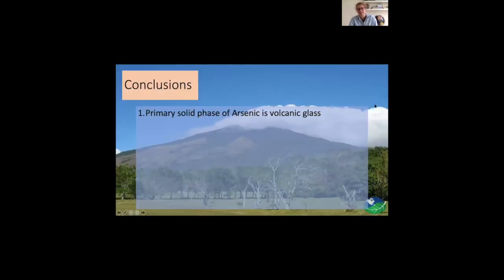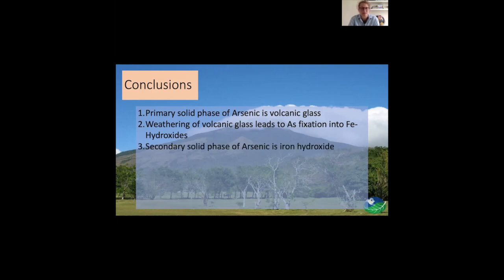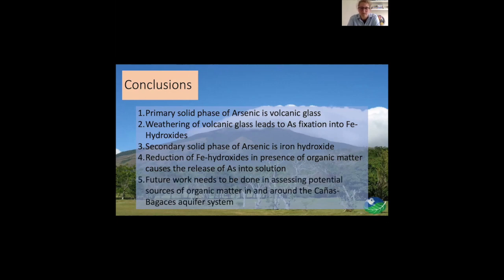So the conclusions of my thesis are that the primary solid phase of arsenic is volcanic glass. Weathering of volcanic glass leads to arsenic fixating onto the iron hydroxides. Then the secondary solid phase of arsenic is iron hydroxide, so it's sticking to these goethite minerals. Then the reduction of iron hydroxides in the presence of organic matter causes the release of arsenic into the water solution. And lastly, there needs to be future work done in assessing the potential source of organic matter. What is contributing? Is it landfill? Is it sewage? Is it just local trash pickup that is getting into the water supply and causing the release of these dangerous levels of arsenic?